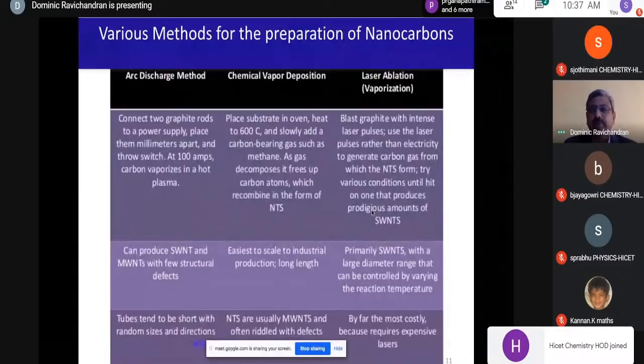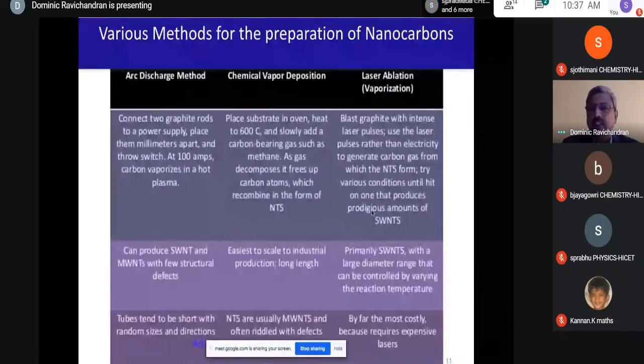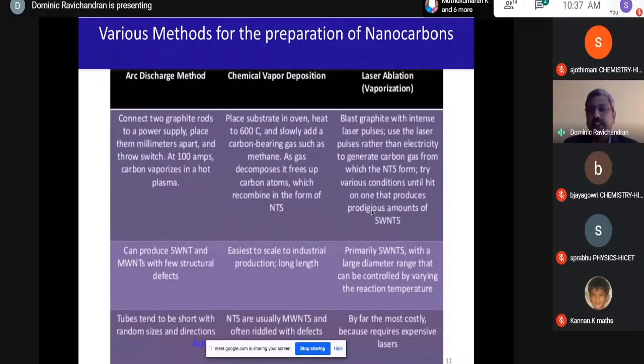And in case of laser ablation, we use what is called a laser pulse, which is used to blast the graphite, and it produces nanotubes and is mainly used for producing single wall nanotubes. And this is producing primarily the single wall nanotubes with large diameter range and a high purity.